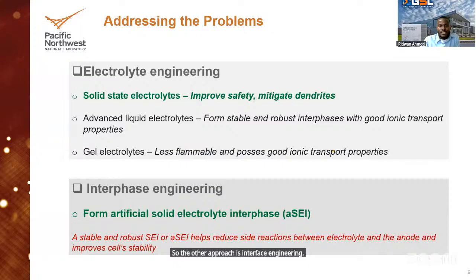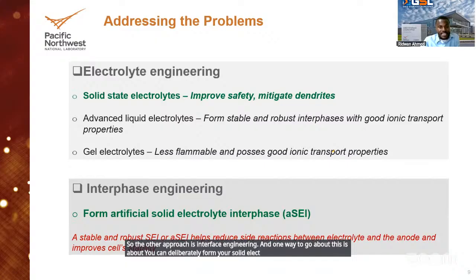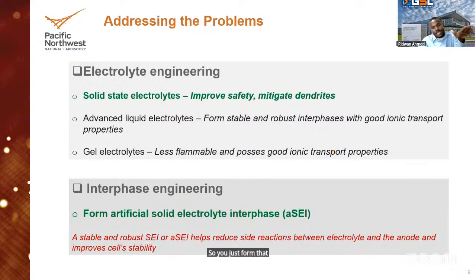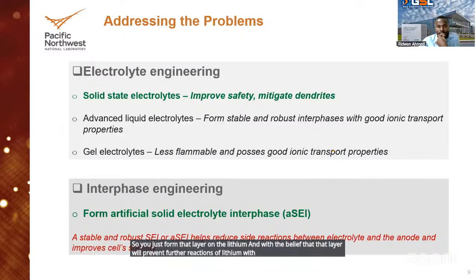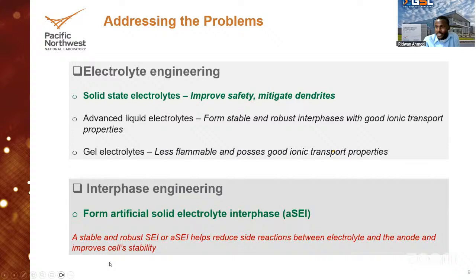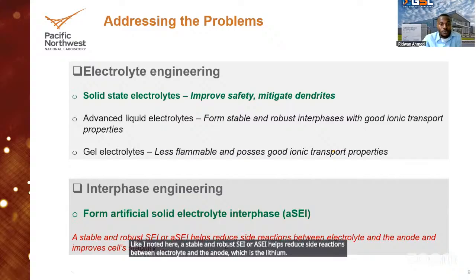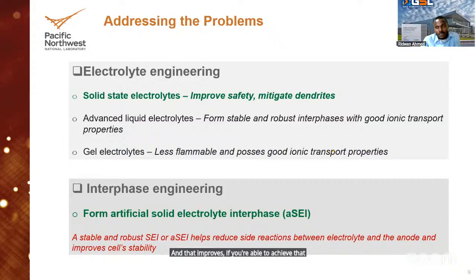So the other approach is interface engineering. One way to go about this is you can deliberately form your solid electrolyte interface, and that is called an artificial solid electrolyte interface. So you just form that layer on the lithium, with the belief that that layer will prevent further reactions of the lithium with the electrolyte. And like I noted here, a stable and robust SEI, or ASEI, helps reduce side reactions between the electrolyte and the anode, which is the lithium. If you're able to achieve that, that would improve the stability of your battery.